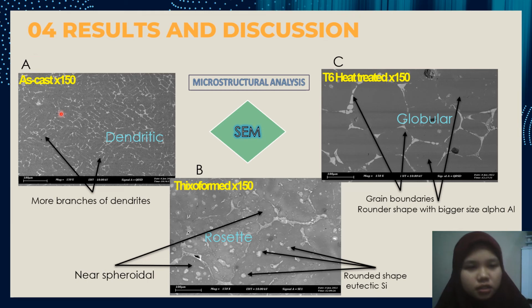As we can see here, there are 3 figures. First of all, figure A for as-cast, figure B for THIXOFORMED, and figure C for T6 heat treated. And we can see that there is dendritic formation in figure A. We can see more branches of dendrites. And as for figure B for the THIXOFORMED sample, this is a rosette shape, and it has near spheroidal formation, near globular but not yet globular.